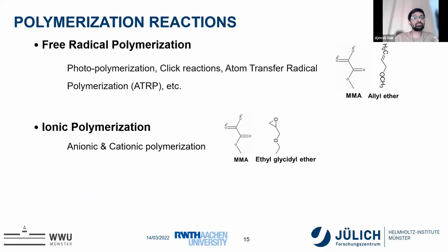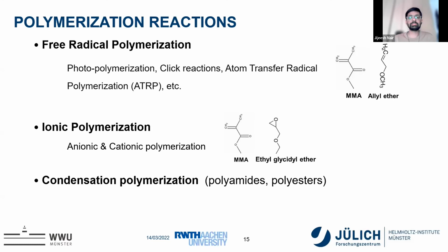Then there is another polymerization, which is ionic polymerization, which is the least used, where you can use methyl methacrylate or even glycidyl ether epoxides. And these epoxides can even be polymerized using lithium salt itself. So you don't need to use additional materials as an initiator to continue the polymerization. So you reduce the complexity of the formulation by using lithium salt itself as an initiator. Then there are classical condensation reactions where you can produce polyesters, polyurethane, etc. Even those materials can be explored further, or you can use in situ electropolymerization, another kind of technique, to modify the electrode surface.